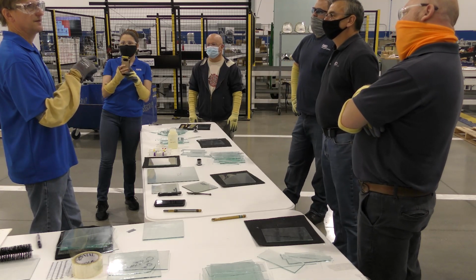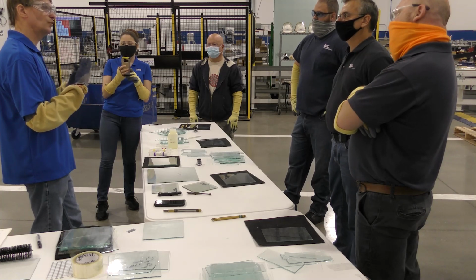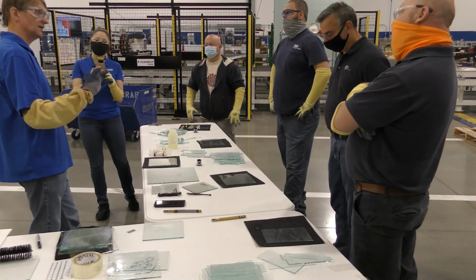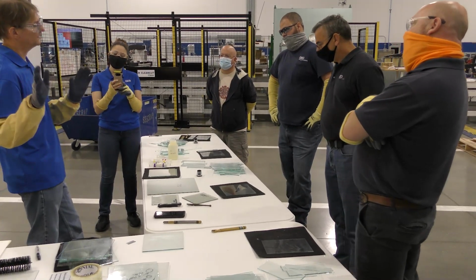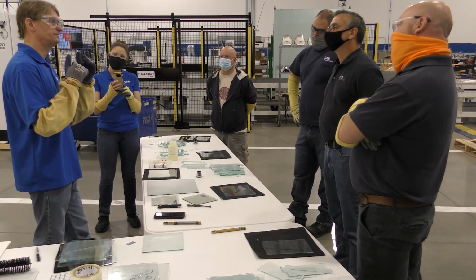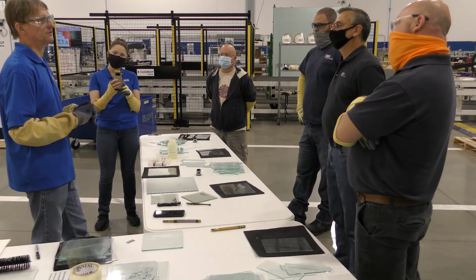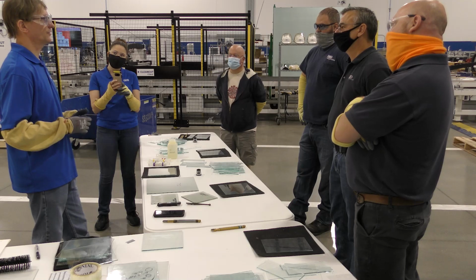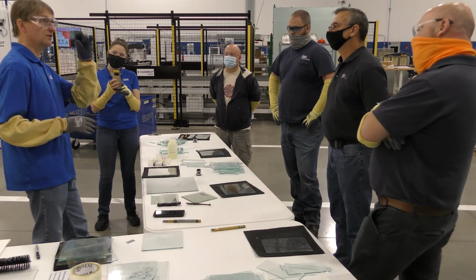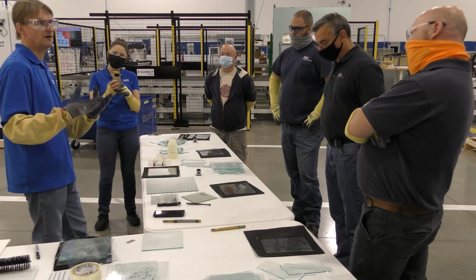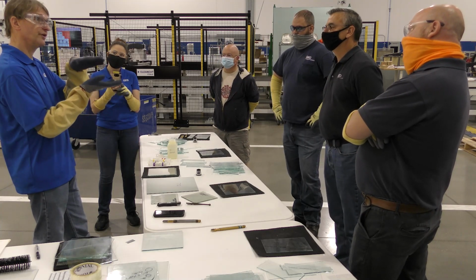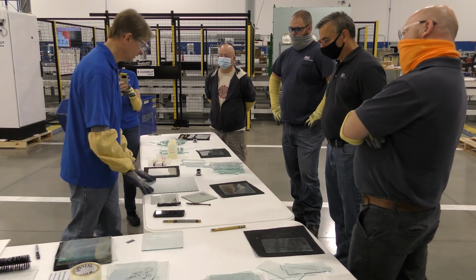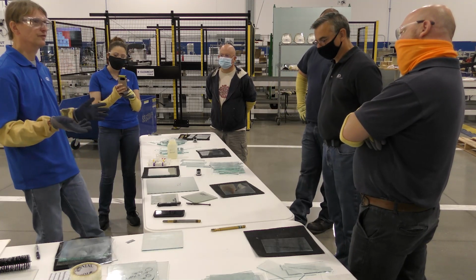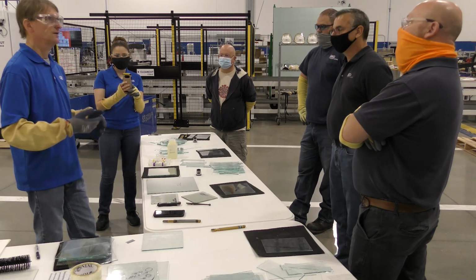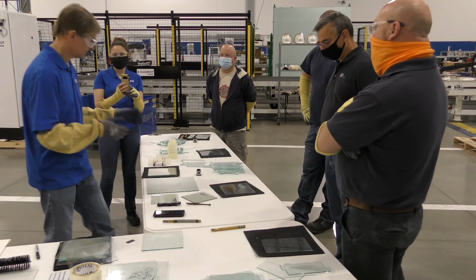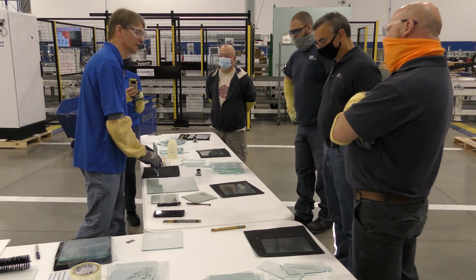So that's why 2.5 mil might be good to use the same wheel diameter as a 3 mil. But then you get into 4 and 5 mil, and you start to get into, hey, this is getting a little bit bad. So 2.5 mil has a relatively thicker compressive layer than 3 mil, proportionally to the thickness of the glass, okay? Because it's thinner and it doesn't have so much of a heat sink to hold the heat, so it cools down a little bit quicker. So that's some of the why 2.5 works just as good as 3 with the same wheel. Because it's just a little bit of mass stress dynamic going on.